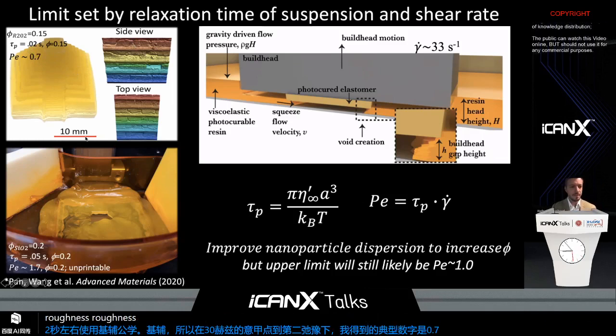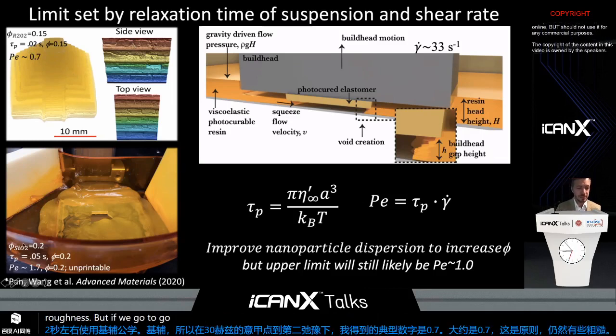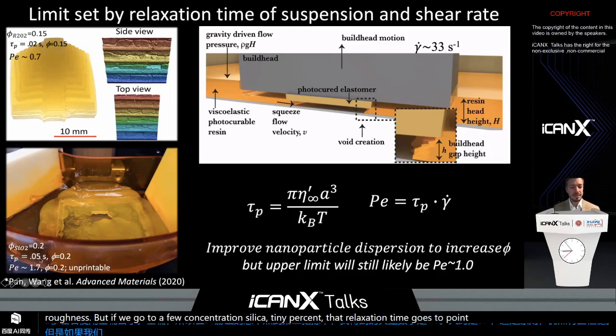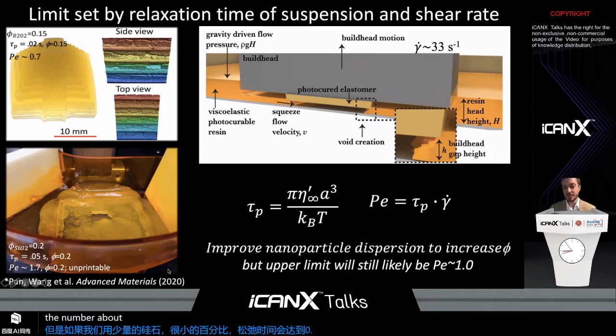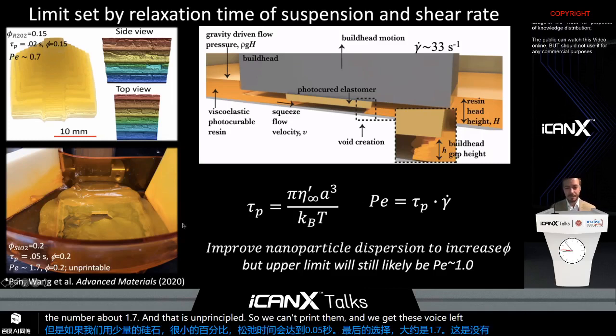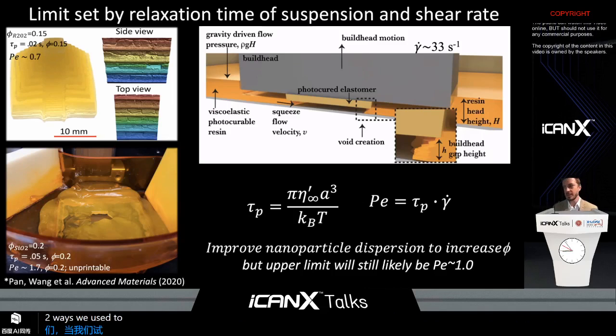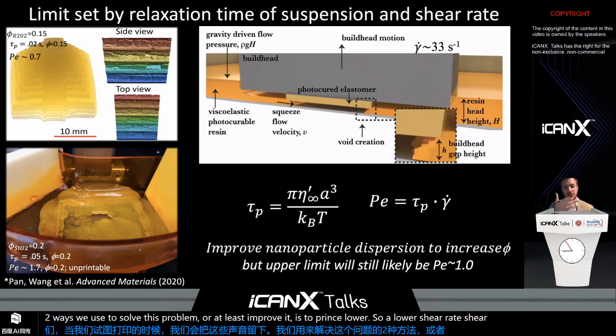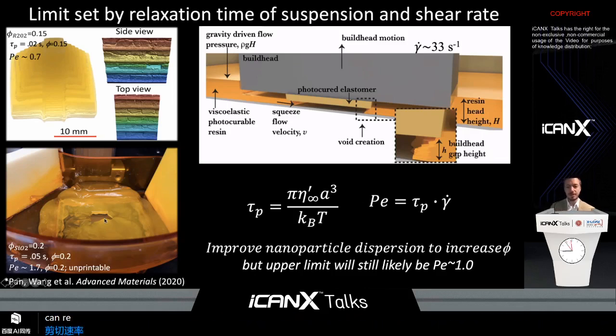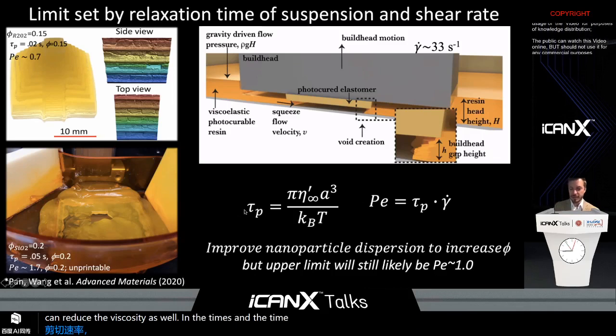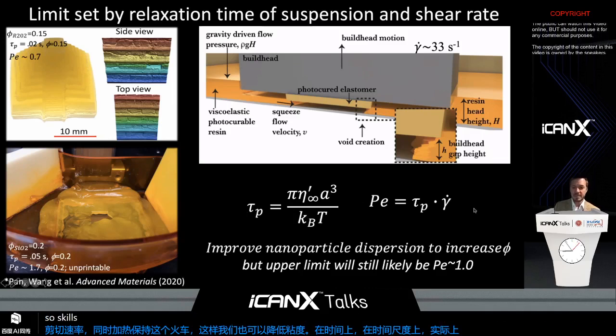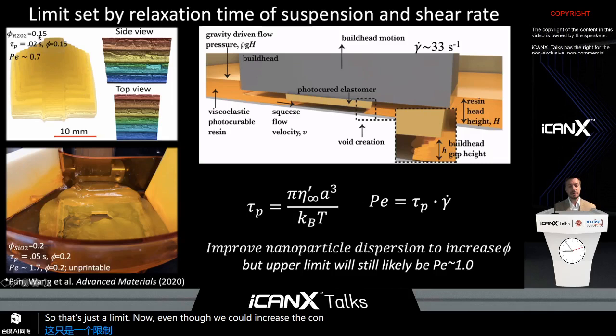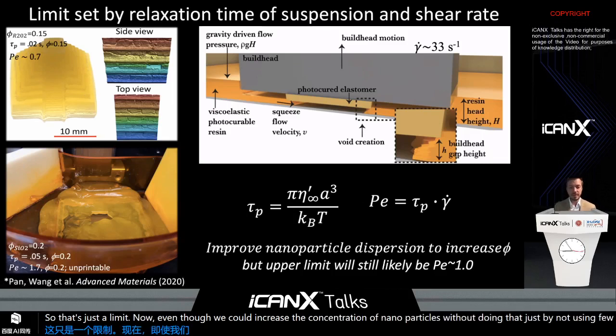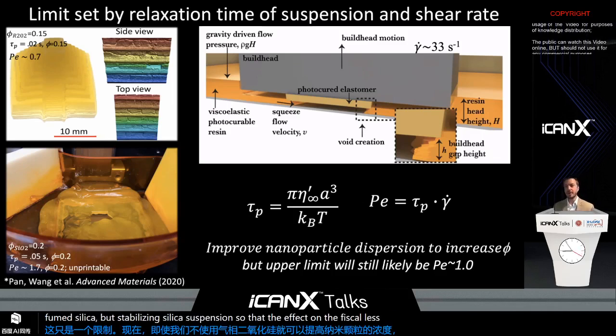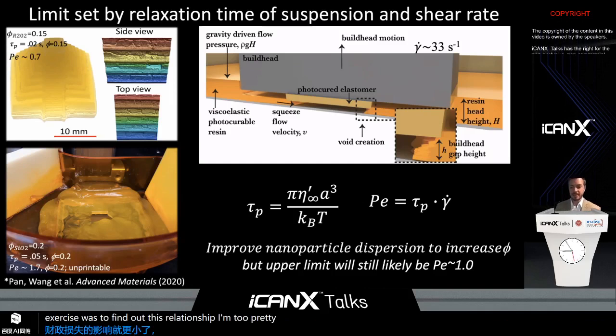Still some roughness, but if we go to a higher concentration silica of 20%, and that relaxation time goes to 0.05 seconds, with a resulting Peclet number of about 1.7, that is unprintable. So we can't print that, and we get these voids left over when we try to print it. The two ways we've used to solve this problem, or at least improve it, are to print slower, so a lower shear rate, and then also heat this tray so we can reduce the viscosity as well, and the time scale. Actually, that's much more important, this relaxation time scale. So that sets the limit. Now, we could increase the concentration of nanoparticles without doing that, just by not using fumed silica, but stabilizing silica suspension so that the effect on the viscoelasticity per volume fraction is less. But the point of this exercise was to find out this relationship to printing and viscoelasticity.